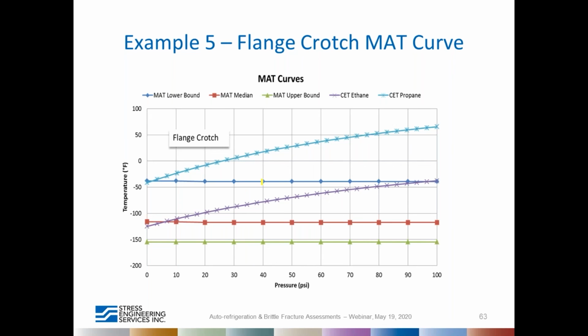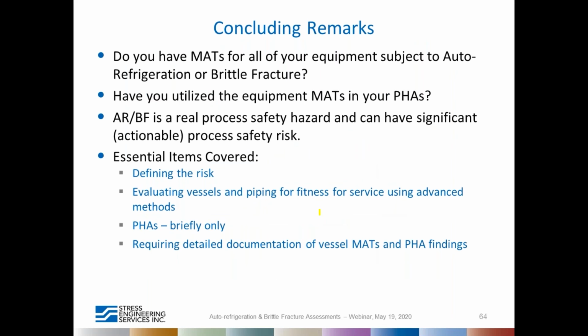However, this assessment involved several conservatisms. So if one were to relax some of those conservatisms, it may bring down the MAT curves below at least one of these olefin CET curves. Care should be exercised when doing such analysis. However, for material quality reasons, brittle fracture assessment shall be performed based on level 3 assessments. And that would be the end of the discussion, and the concluding remarks are presented here.